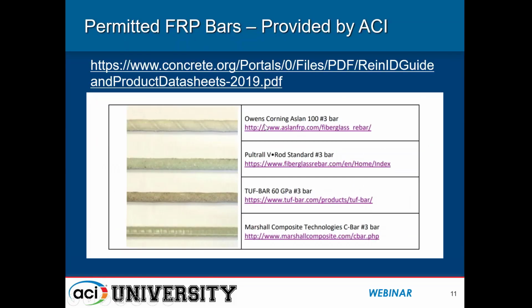So you can see it with the Owens Corning, the Aslan bar. It has a helical wrap as well as a sand coating. The Pultrall bar has a sand coating, and the TUF-BAR has a darker sand coating. They may not coat these bars any more so than they already are by the manufacturer. The Marshall C bar does not have a sand coating. As you can see on the screen, and on the webinar screen, it has ribs very traditional to a steel reinforcing bar. They are not allowed to coat these bars. They must use them as is in their concrete.